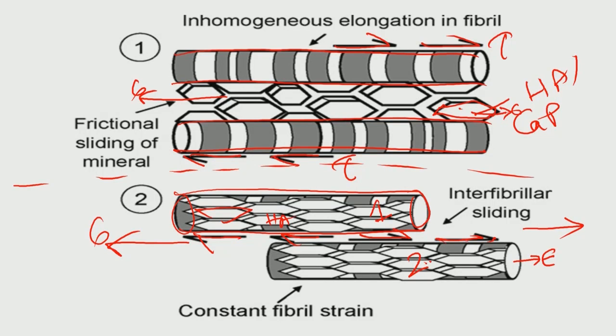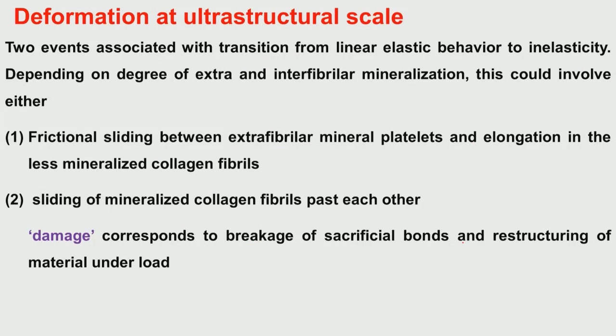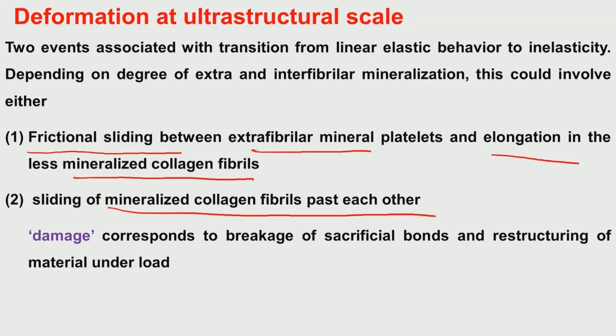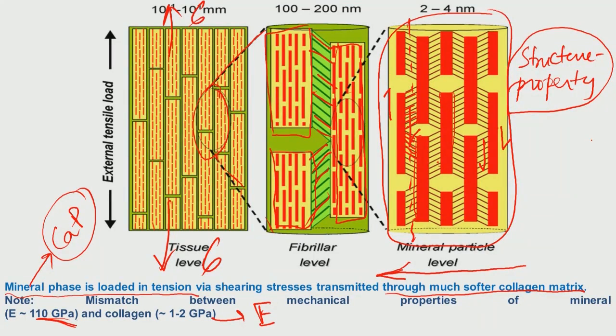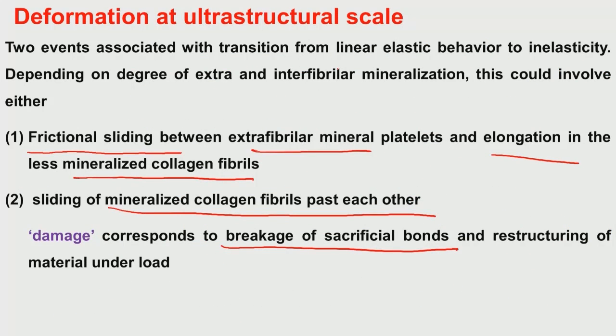The hydroxyapatite is contained within this collagen bundle. Therefore, deformation at the ultrastructural level can be described by two events, as I explained to you in the last slide. One is the frictional sliding between the extrafibrillar mineral platelets and elongation of the less mineralized collagen fibrils, and the second is the mineralized collagen fibrils sliding past each other. So, damage of the bone structure essentially corresponds to the breakage of the sacrificial bonds. Sacrificial bonds are the kind of bonds I have mentioned here. So this is the breakage of the sacrificial bonds and restructuring of the material under load.